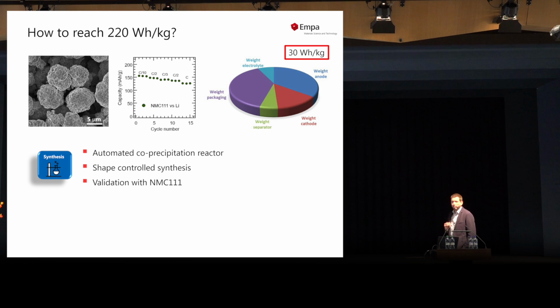So the problem is when we now work on lab cell batteries, we typically make electrodes, typically a square centimeter in size, and pack them in something like a lab cell battery, something that looks like coin cell batteries you can buy from Migros or Coop. And when you then try to assess the energy of the cell, you get relatively low values. The point is that the packaging in lab cells takes a big part of the battery, and this is actually an optimistic approximation because I did not include the excess of electrolyte that we usually use in lab cells.